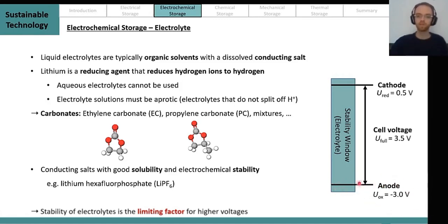So you see it lies within the stability window of the electrolyte, and therefore we can consider it stable against the anode. Now we have a cathode which maybe has a reduction potential of plus 0.5 volts. That means our overall cell voltage is 3.5 volts. Our cathode voltage also lies within the stability window of the electrolyte, and therefore it's also stable against the voltage our cathode provides. The issue arises if we want to further increase our cell voltage. Say we want to establish a cathode material which has a reduction potential of 1 volt. This will lead us to a much higher cell voltage.